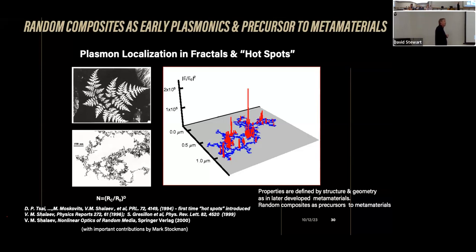And what we showed at that time is that the fractal morphology actually promotes localization of collective plasmon excitations. Particles are very small, like 10 nanometers in size. And these collective excitations, instead of being spread over the whole sample, are concentrated in exceptionally small areas, which we refer to as hotspots. And the local field in these hotspots could be orders of magnitude higher than the incident field, resulting in dramatically enhanced surface enhanced Raman scattering, dramatically enhanced nonlinear responses, and so on.